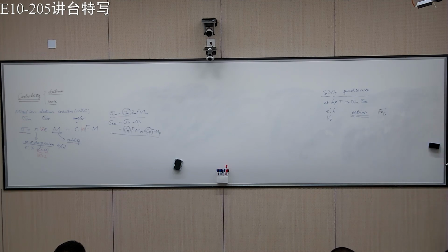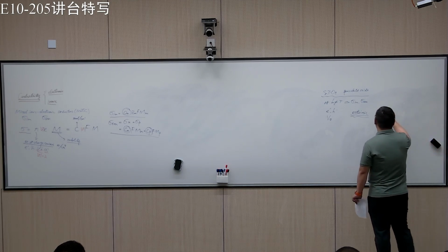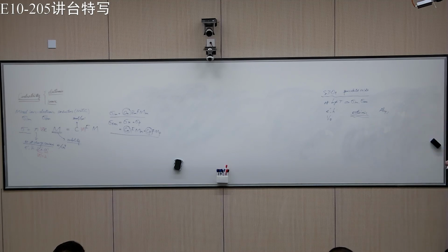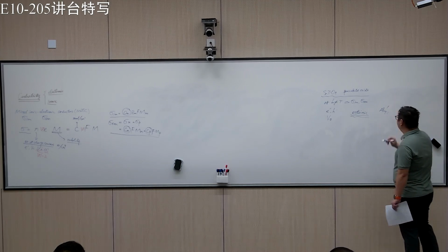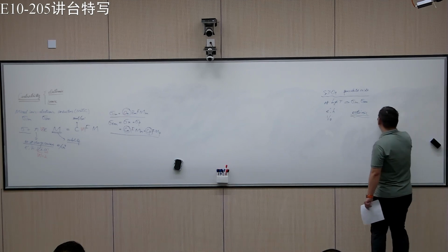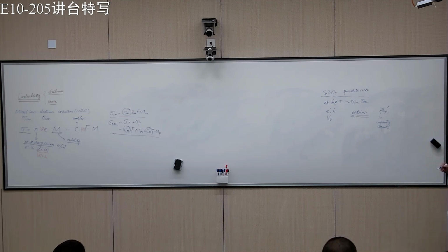Let's say it's aluminum, because iron is complicated. Aluminum is 3+, titanium is 4+, so it has one negative charge. If you have aluminum as an impurity, you can also call it a dopant. Whether you like it or not, you have this in your structure.